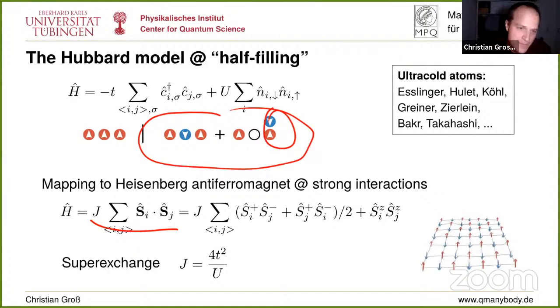If you're then in the spin language, there's an atom on each site, but of course the spins can still move. The spins can move by a superexchange process, as shown here. This blue one hops on top of the red one, and now the red one hops away. So that means 2 hops, a t squared process, and it costs this penalty U. This gives you the energy of the superexchange. And now we have all relevant energy scales in this model: the t, the J, and the U.